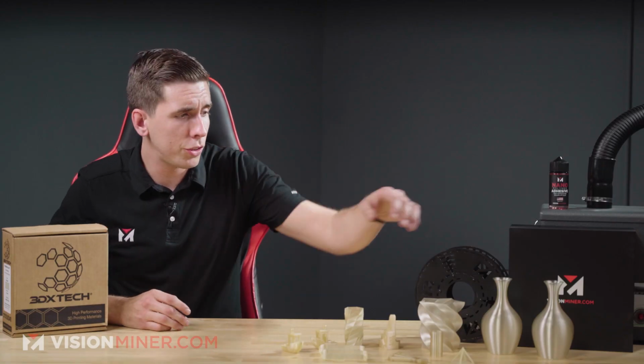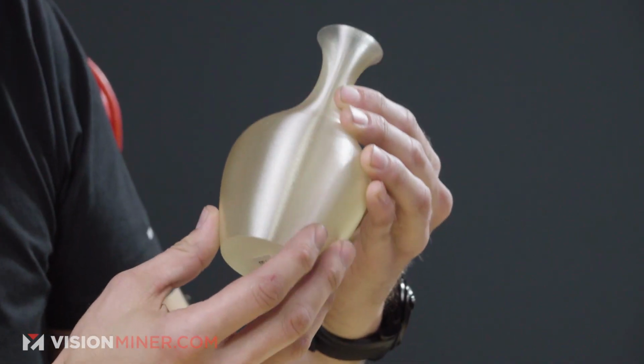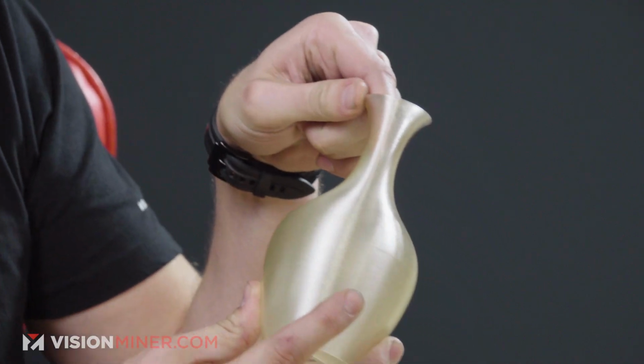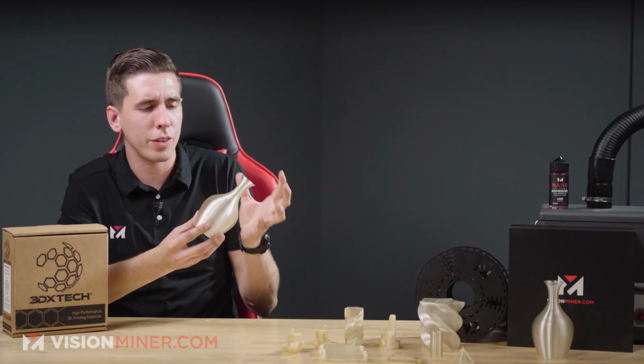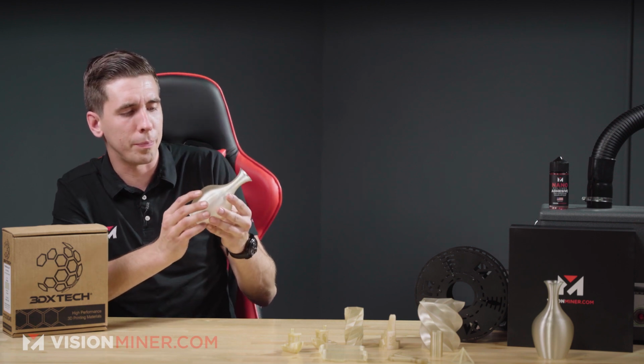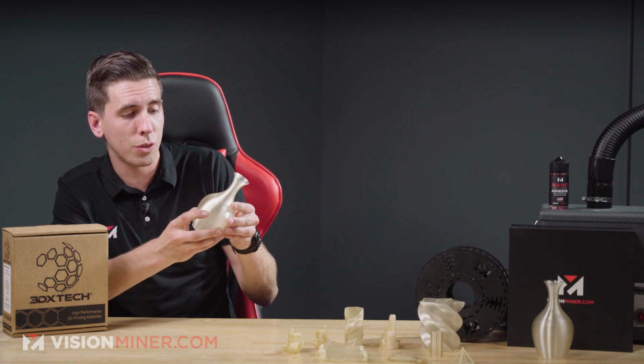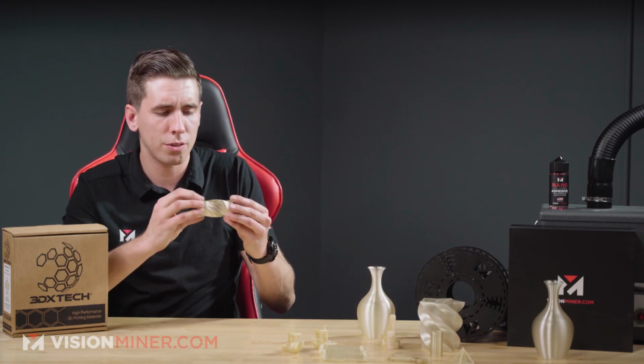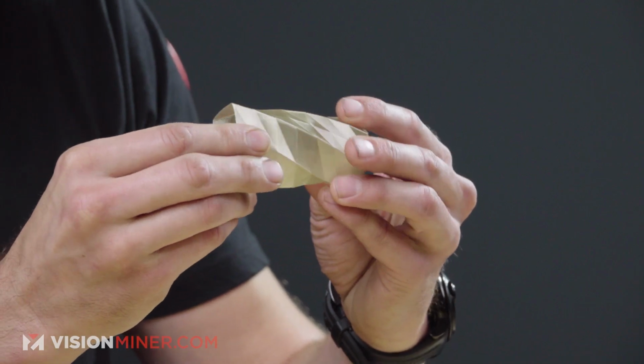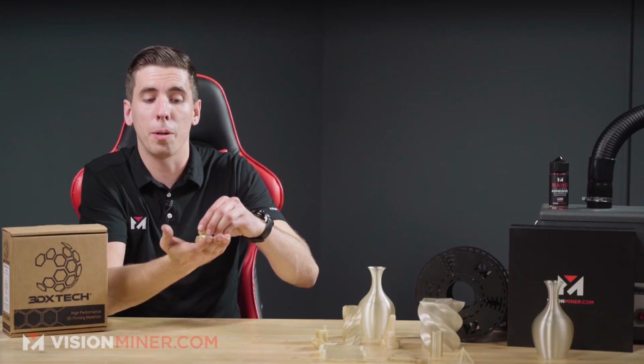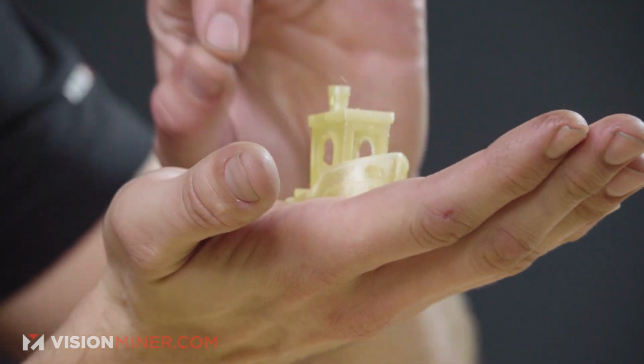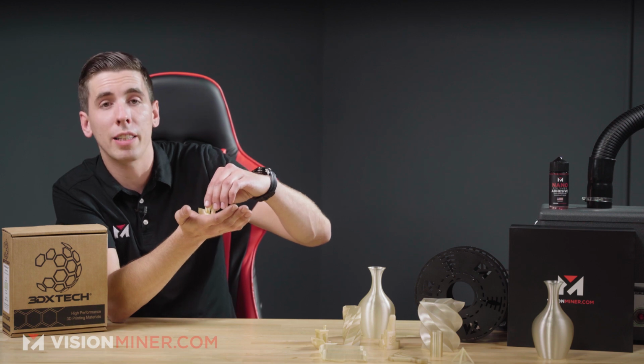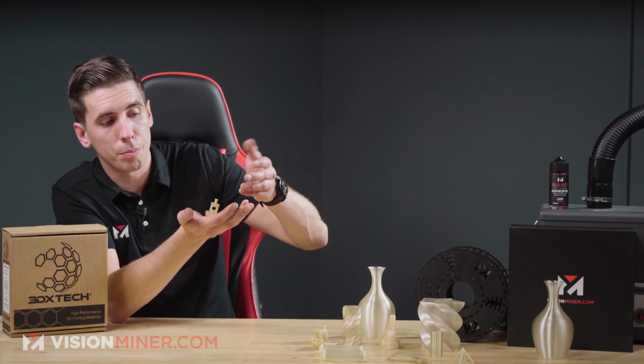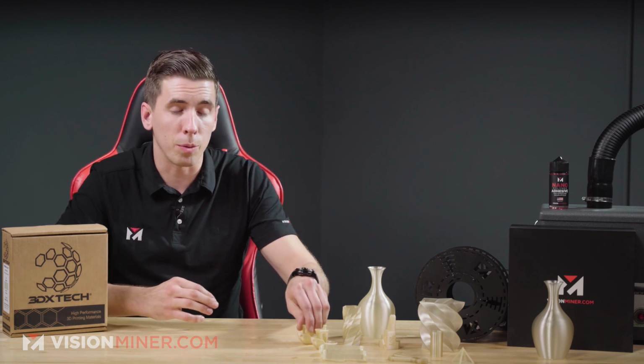Okay, so we've got a variety of parts just so you can see the fit and finish of the actual material. This stuff comes out relatively translucent. You can sort of see my finger through there. It does have a bit of a yellow hue to it, and it's pretty darn strong. We've got some really cool parts here. I mean, it's beautiful, the surface finish you can get out of this stuff. And obviously we've got the obligatory benchy. As you can see, overhangs aren't the best, but they still do pretty good considering, a lot better than material like PEEK or something like that. So supports are not totally necessary. We do have high temp supports available on the site for this material, but a lot of the time it's amazing what you can get away with a single extruder.